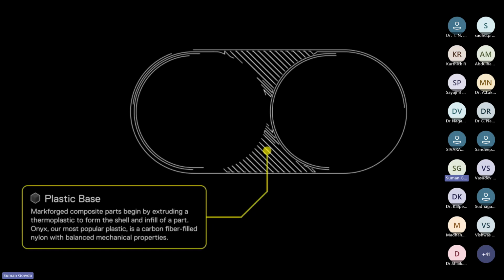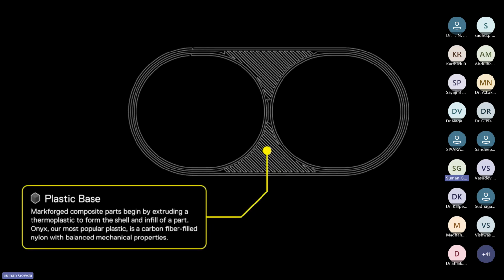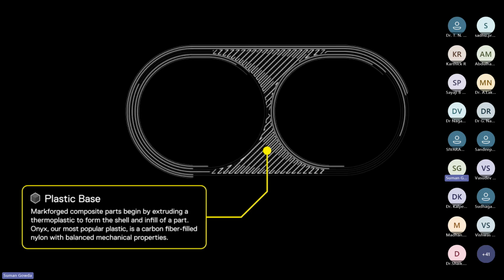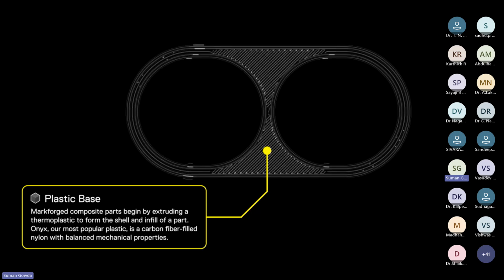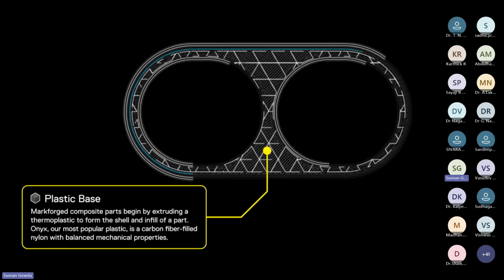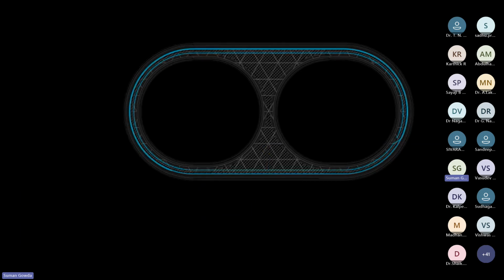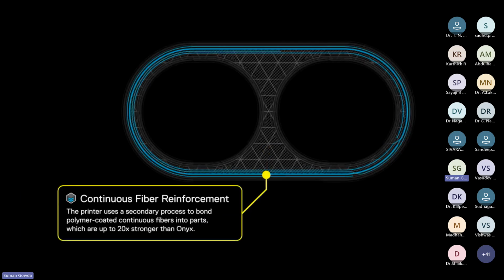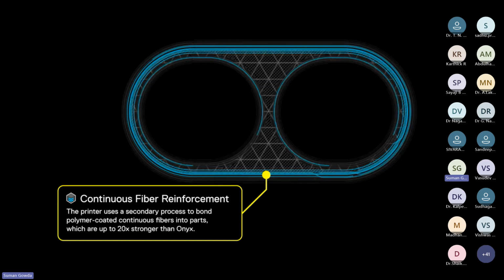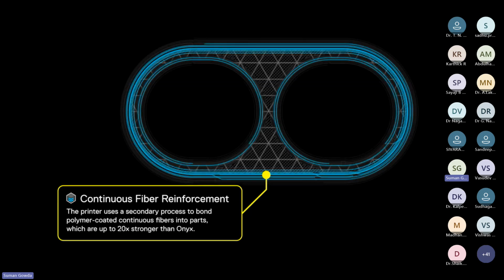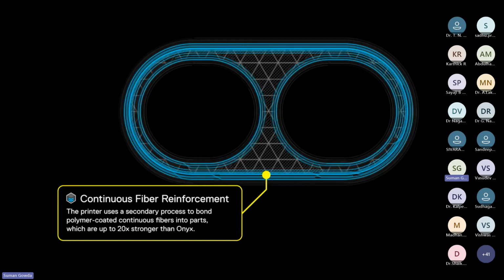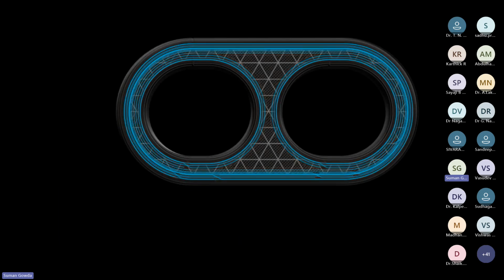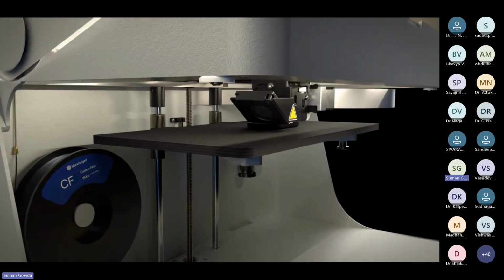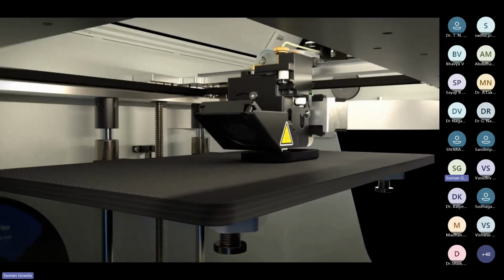Okay, so this is the base material, what we have the onyx, which is the black material, and then we deposit around 3 to 4 layers of this onyx just to make sure that we have got good amount of bottom surface. And then you can see we have started to deposit this blue line. So these blue lines are actually the fibers. As of now in the settings we have selected fiber only in the boundary, so we are depositing fibers in the boundaries of the part, and then the remaining section is being printed with the onyx. If you closely observe, the external boundary is built with onyx.